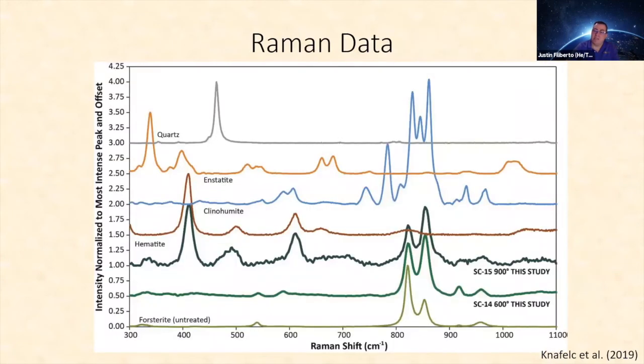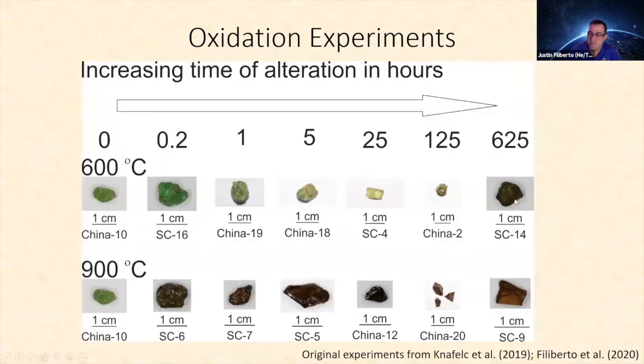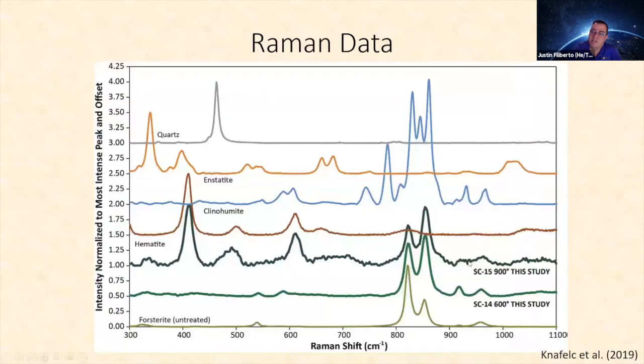When we look at Raman data, these are our normalized peaks, and these are just spread out this direction so you can see them. These are examples of other minerals. So this is quartz, enstatite, clinohumite. This is hematite here. This is olivine untreated down here, the nice olivine doublet. This is 600 degrees. This is 900 degrees. This is 14 and 15, so this is this experiment. And we actually did duplicates through this entire thing. So 15 is the duplicate of the month-long experiment at 900 degrees.